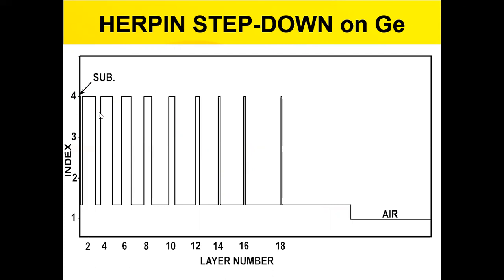These two lows from these two simulations will merge with each other to become just a thicker low index layer. We do the same thing throughout until we get down to the end where the next to last Herpin simulation will have very little high and a lot of low. Then the last one will have all low. So we have approximated the index profile of the Gaussian form.